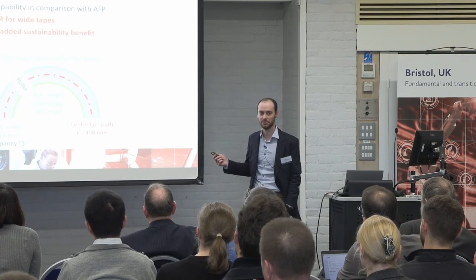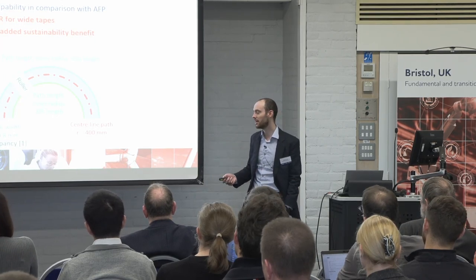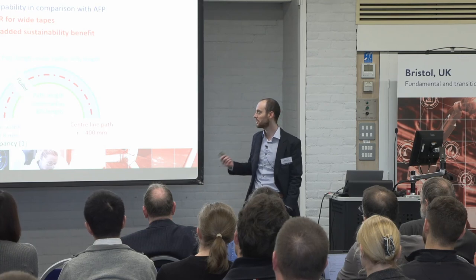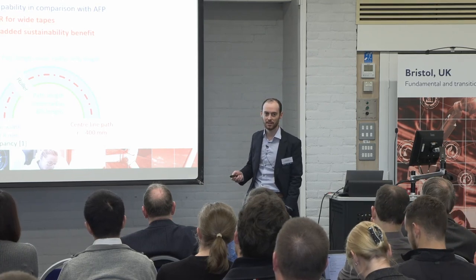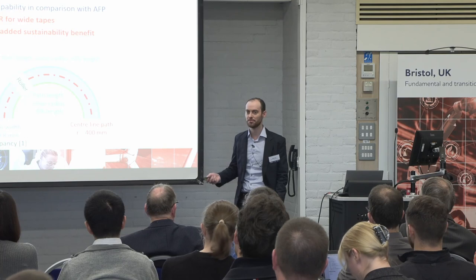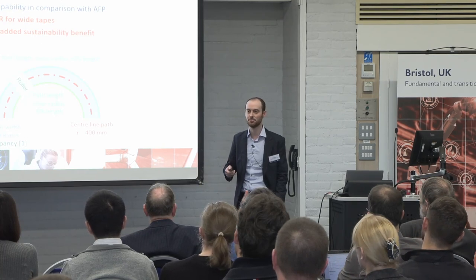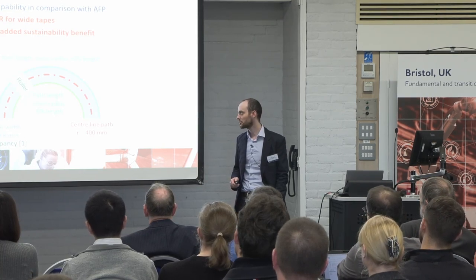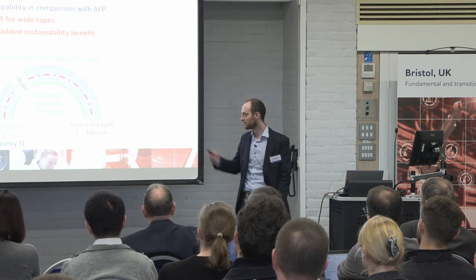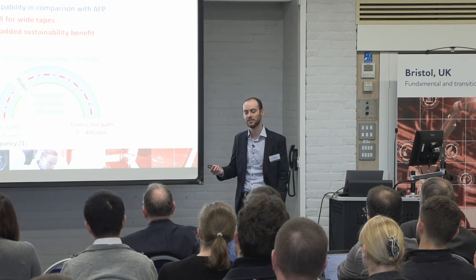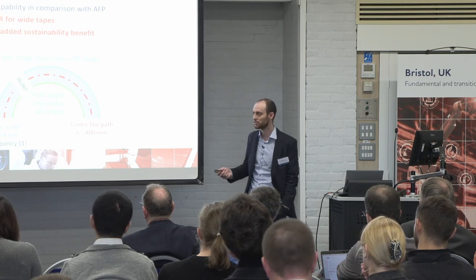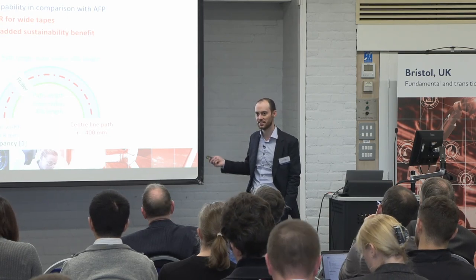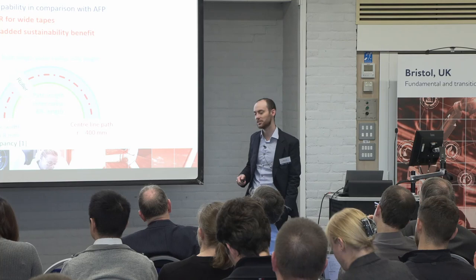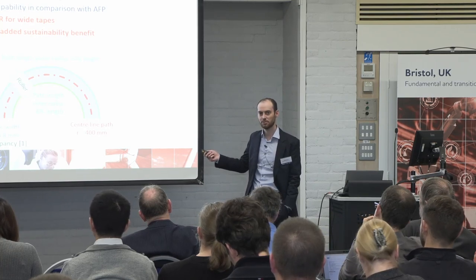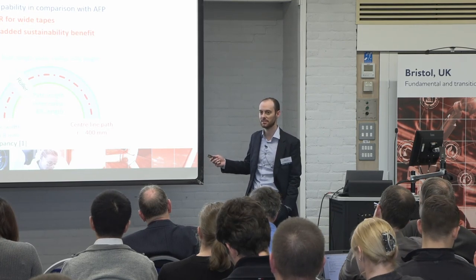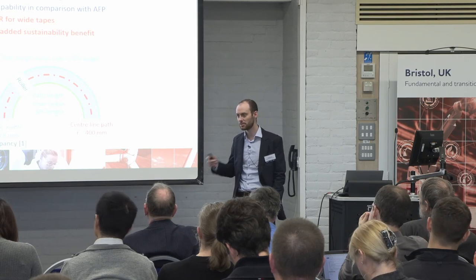And the first aspect is we know, again, rapid tow shearing, ICOMAT, very, very good at steering, so we want to demonstrate that. But also, there's a theory that aligned short fiber recycled materials, such as those produced by Lineat, should have a slightly lower resistance to that 2D shear than a continuous carbon fiber tape or tow would do. So the idea here is we want to, first of all, prove that we can lay recycled short fiber material using an automated layup process, an industrial process as well.